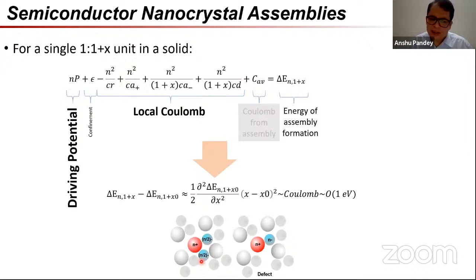If you have an assembly like an AB2 type assembly, now the assembly, of course, is extremely disordered, but suppose I try to make a defect here, which means I try to play with the stoichiometry locally. So I'll try to remove one B nanocrystal so that I have an AB type defect, and there's a B missing, a B vacancy essentially. What do I have to do for it? In order to do it in a fashion where I conserve the charge, I have to pull off all the n by 2 electrons and redump them into only one B dot.